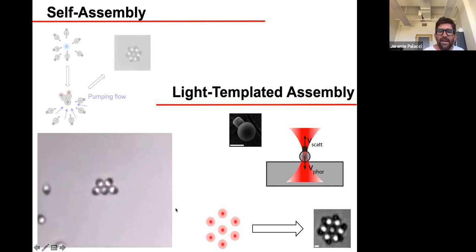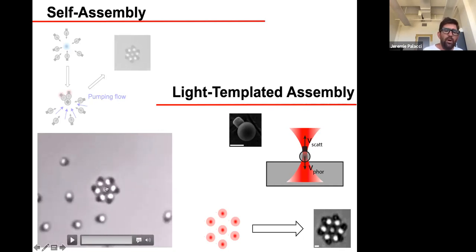And so we can make light patterns and form whatever structure we want and then release the traps and the structure is going to move. And so we can make the particle go one way. We can also control the amplitude. So that's another example here where we write UCSD. So you see that we have those active particles, they run around and then we put a template and the particles will occupy the different positions of our optical trap and we can make whatever structure we want. And then when we release the trap, here they would break down, but if we form the stable machine it will remain.